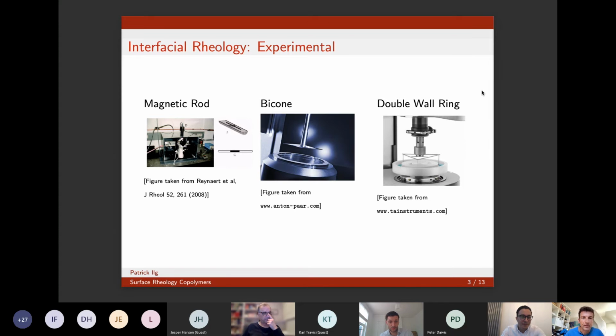So one thing is you take a Langmuir trough and you put a rod here, you make it magnetic, and so you can move it with a magnetic field in plane, and then you measure how much this thing moves for a given perturbation and work out the interface stress from this one. The bicone in the middle is something closer to a usual rheometer, but what you try to do is you try to shear only the interface.